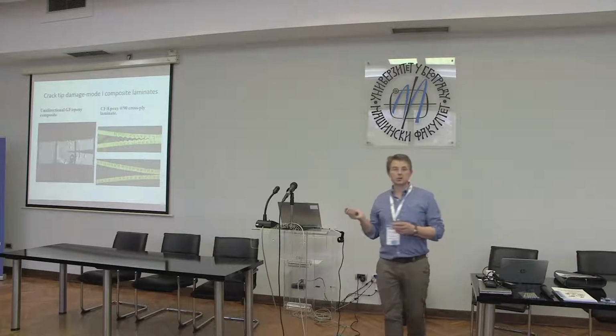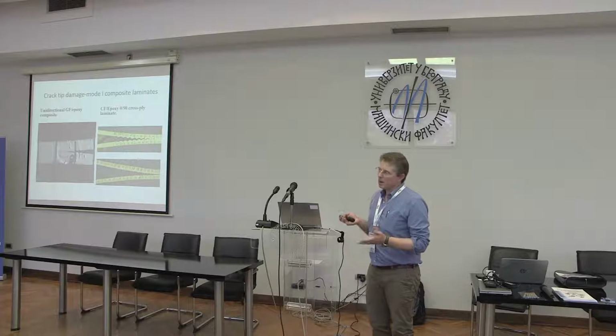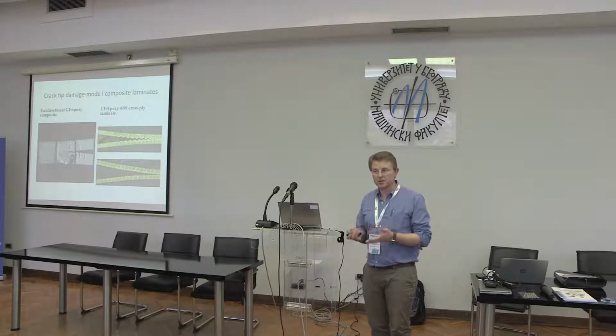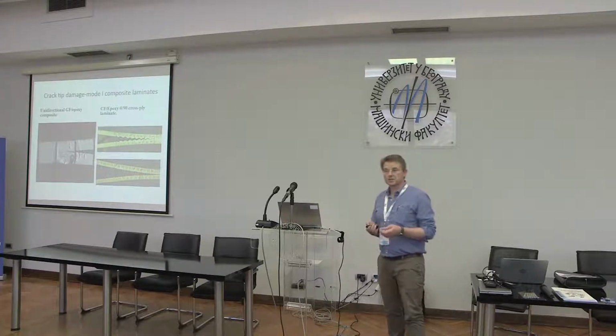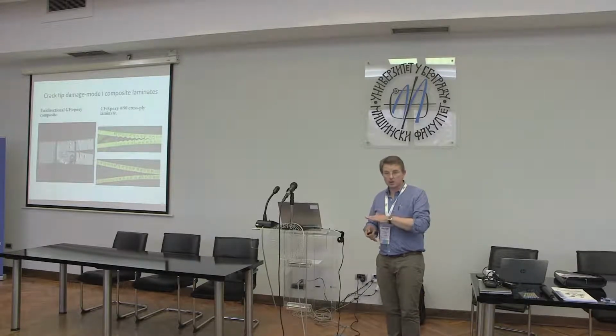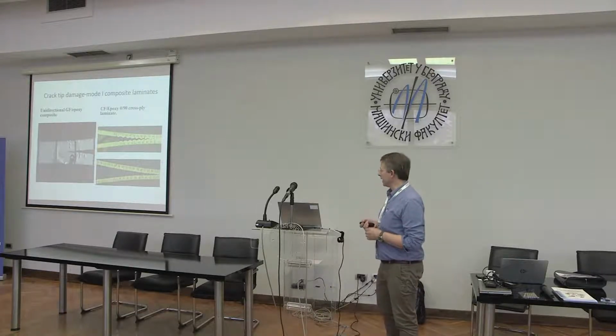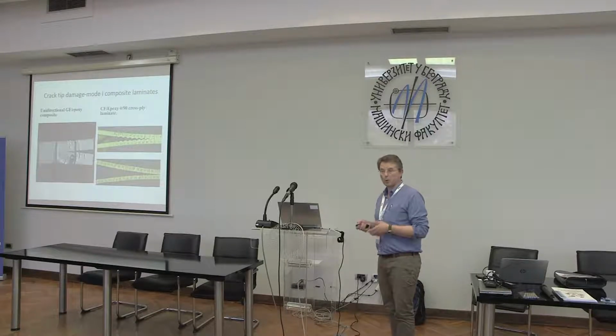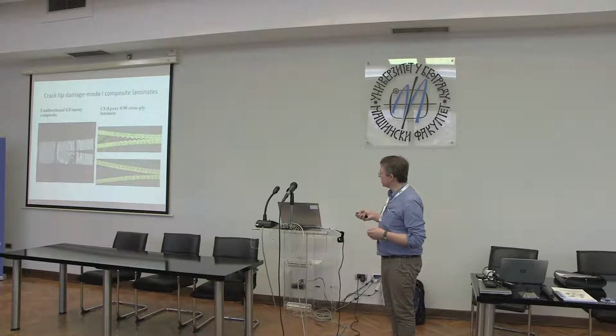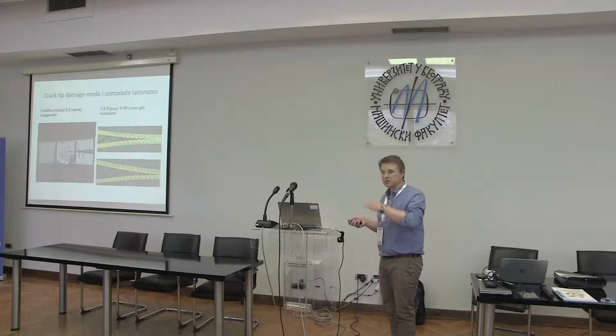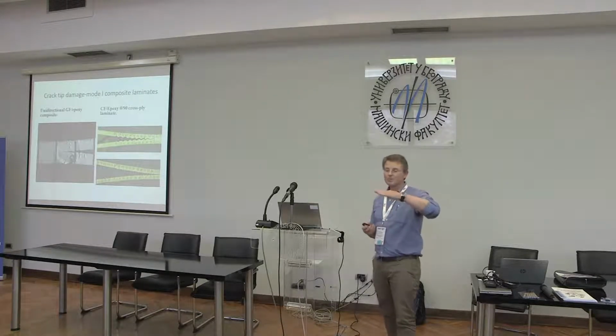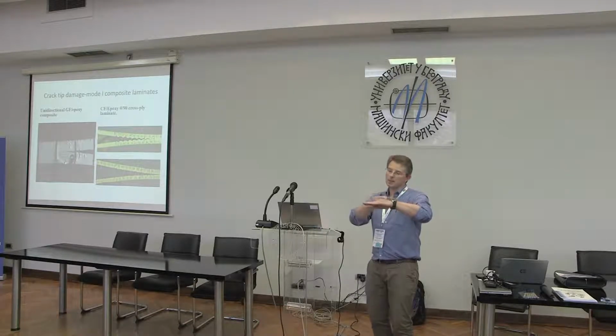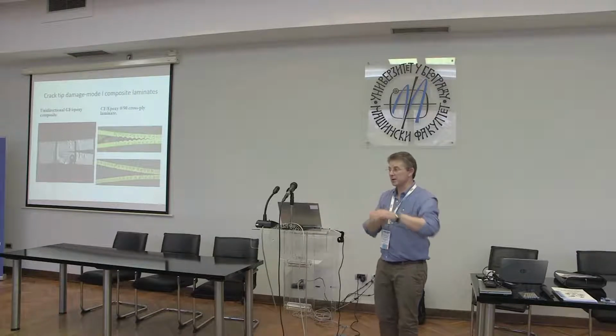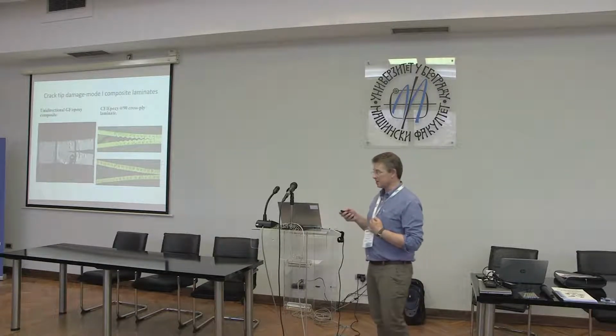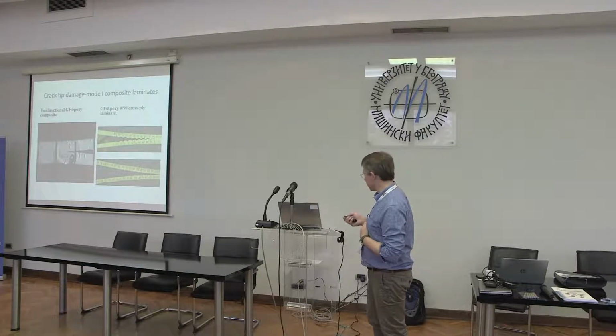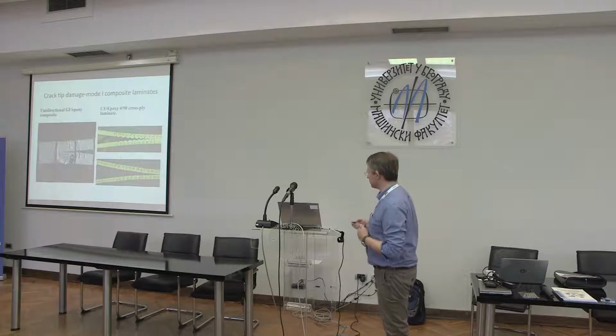Of course, there are other situations where you have non-UD materials. So obviously we're interested in laminate systems where we have 0-90 degree, general multi-directional fibre reinforcement, and of course you have many different types of crack propagation and mechanism. So this can lead to fairly complicated crack shapes. You can see this sort of sinusoidal type of fracture where the fracture is going up and below basically toes of fibres that are going transverse across the specimen. So you're getting a distorted fibre fracture shape, and of course this is also leading to fibre bridging.